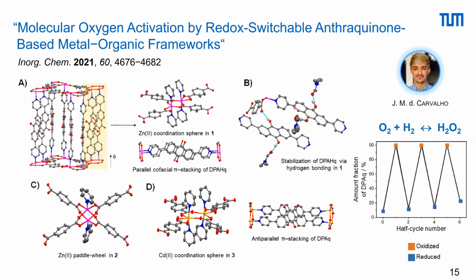And this is important because here you can then switch between the two states, the reduced and the oxidized stage of the anthraquinone. In a way, you can integrate the process of the direct conversion of oxygen and hydrogen to hydrogen peroxide into a metal organic framework. So he has been able to show that you can switch between this oxidized and reduced status of the framework depending on the conditions of the system, and he was able to detect the formation of the hydrogen peroxide. Unfortunately, this process is not yet catalytic, but that would be an obvious goal we want to achieve. Molecular oxygen activation by redox switchable anthraquinone-based metal organic frameworks was the title of his Inorganic Chemistry paper.